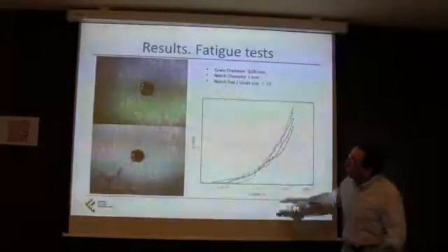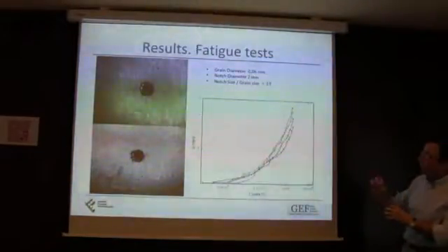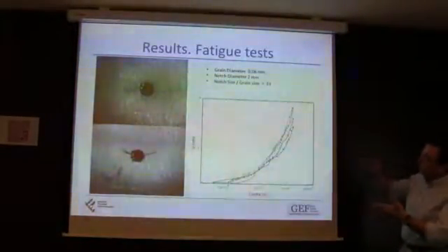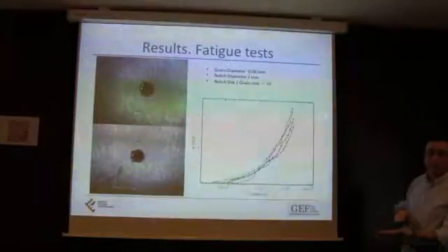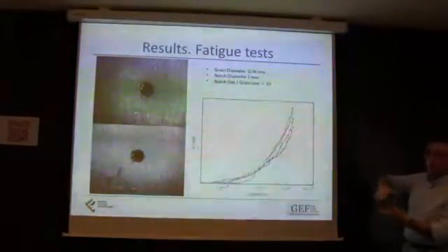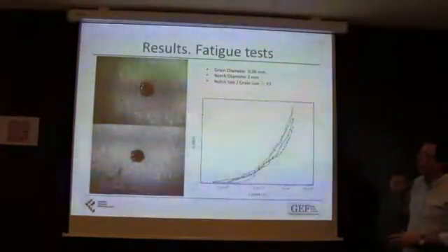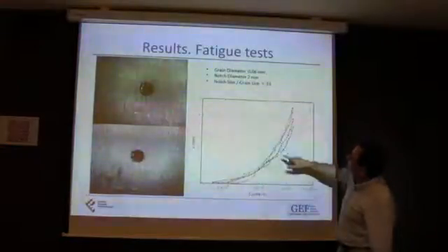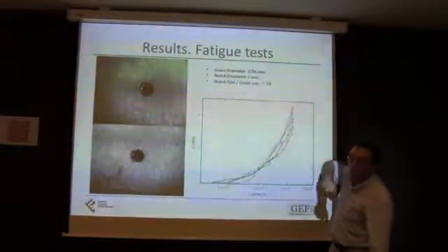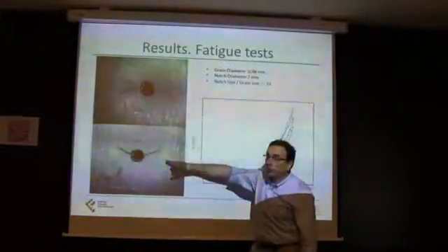So what we've done here is we've got the same size for the hole, and we've produced this hole in different microstructural sizes. So doing that, you can see the whole behavior from long cracks to short cracks, microstructural short crack, right? In this case, the microstructure is very small; it's only 60 microns, and then you get the crack growing mainly in mode 1 from the beginning.